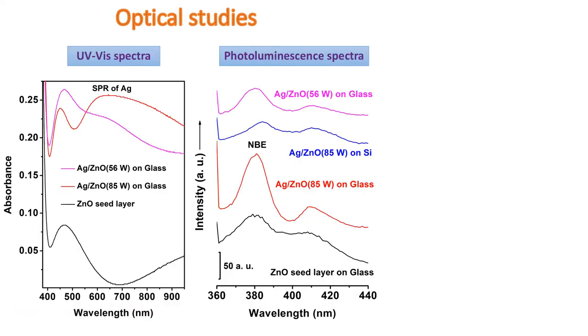The optical properties of silver zinc oxide heterostructures are determined using UV-visible spectroscopy and photoluminescence spectroscopy. In the UV-visible spectra, strong absorption is observed at 380 nanometers, which is attributed to the fundamental absorption edge of zinc oxide. The plasmon peak of silver is situated at around 538 nanometers. The SPR wavelength of noble metal nanoparticles can be tuned by tailoring the size, shape, inter-particle spacing, and the surrounding medium. An interference pattern is observed in the spectra for silver zinc oxide heterostructures. The second peak at around 632 nanometers might be due to the surface plasmon resonance of silver nanoparticles. The plasmon peak of silver zinc oxide heterostructures is further shifted towards red, which may be due to charge transfer from silver nanoparticles to zinc oxide microrods.